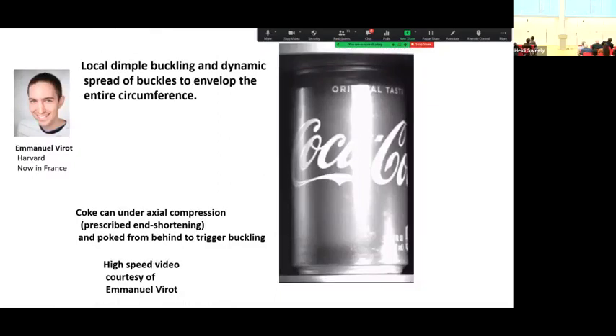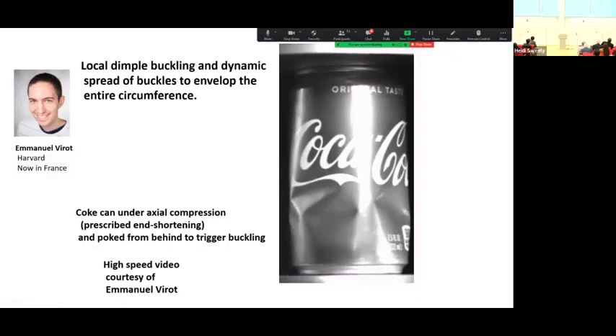Here's an example of this. The probe, by the way, is coming from behind. So this is a dynamic picture. This is taking place in just milliseconds. And so what's happened there is it's probed from behind. It starts to buckle locally. These short wavelength modes dynamically sweep around the can. Notice that again, this is not prescribed load. As I say, if it had been, it would do that. But this is prescribed end shortening.